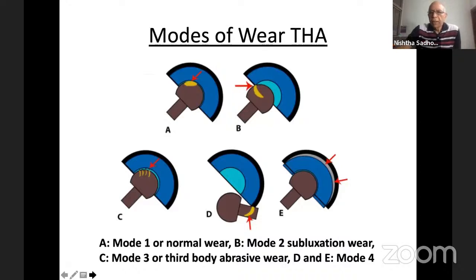The wear, when it happens, happens in different ways. The so-called normal wear is when the wear occurs at the normal so-called superolateral aspect of the prosthesis, where the weight-bearing line is. Or it can be a subluxation wear, that is there is more of a kind of edge loading. So there is a lot more concentration at a lot less area. So the wear would be accelerated.